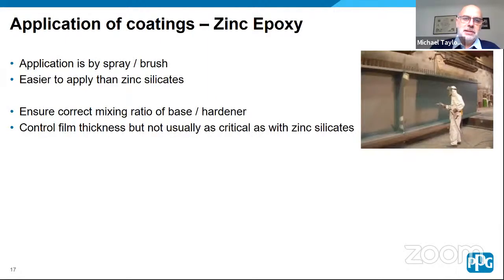Zinc epoxy coatings tend to be a bit easier to apply. That's one of their advantages. Again, usually by spray. You can apply them by brush. You have to make sure you mix the base and hardener at the right ratio and use the right thinners. The control of the film thickness, you have to control it, but it's not usually quite as critical as with zinc silicates. You can apply slightly higher film build and get away with it, shall we say.